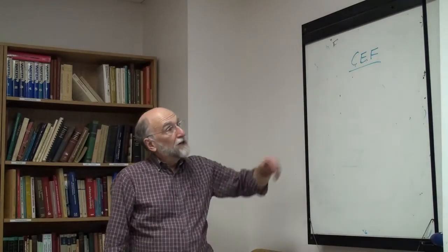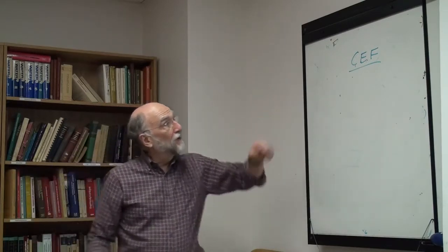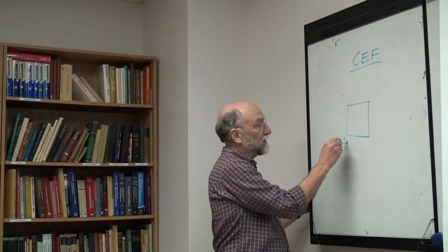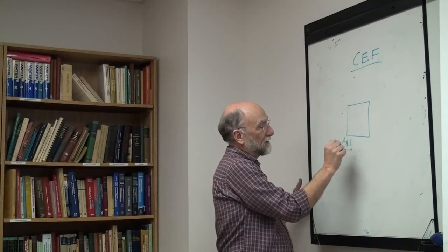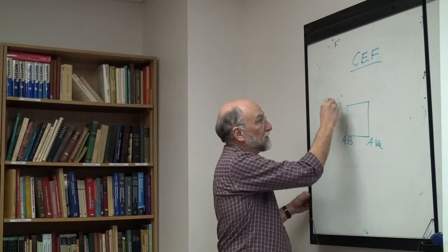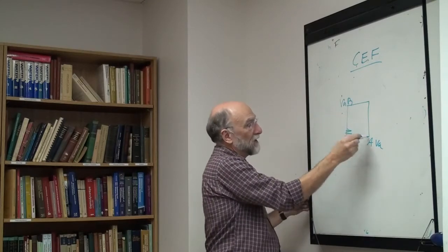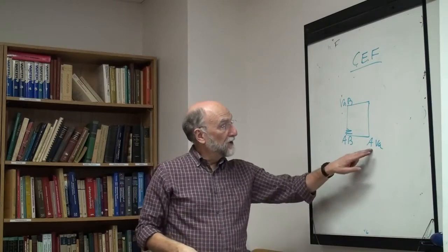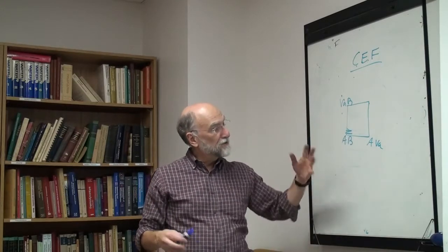We've applied the compound energy formalism to things like molten salts, where the end members are actually real components, like sodium chloride, potassium bromide. We've applied it to things where the end members are hypothetical, like this would be AB, and over here you've got A vacancy, and this is vacancy B. These are all hypothetical compounds, but they're still neutral things.